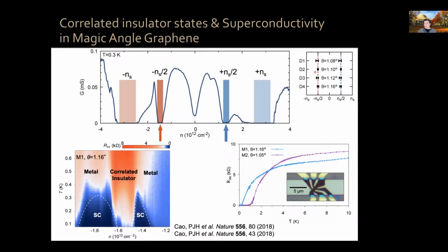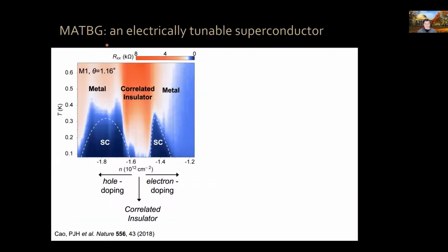Now, this occurs only for a narrow range of angles around 1.1 degrees. If you move further away from that region, then you don't really see this behavior. Magic angle twisted bilayer graphene is an electrically tunable superconductor. That means that when we put a certain number of electrons per unit cell in our system, we get a correlated insulator state. And now, as we add electrons or holes, which we can do electrostatically because we form a parallel plate capacitor between the magic angle graphene and a metallic gate, we have a field effect transistor geometry, and we can change the number of carriers electronically. We can realize these electrically tunable superconducting domes.